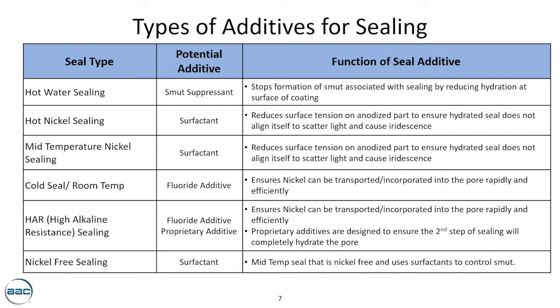Hot nickel sealing and mid-temp sealing. Both of these types of sealing require a surfactant. And the surfactant is used to help reduce surface tension and try to lend itself to getting as much nickel in that coating as possible. The challenges with these surfactants are twofold. One, over time and through heat, they break down. And in the case of the hot nickel, when that breaks down, there's a risk of residue building up on the part.